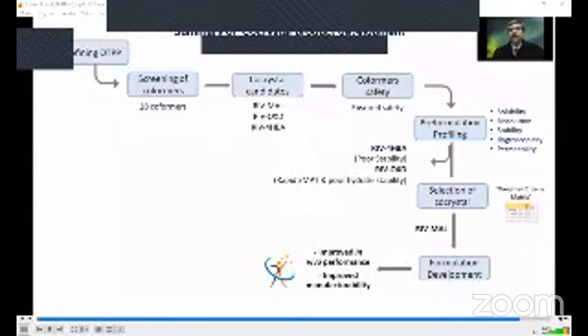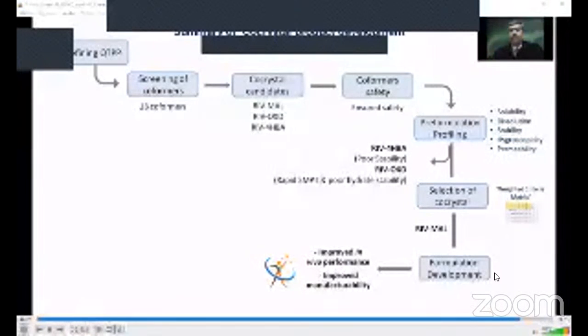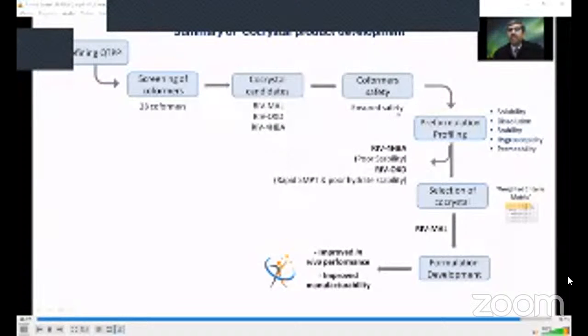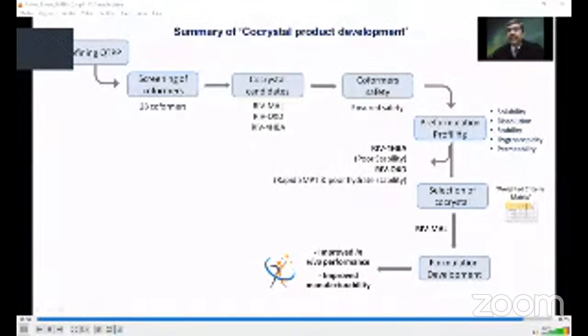Looking at developing a drug product from that co-crystal, the safety of the co-former must be ensured right in the beginning, because later on it is going to give problems with the regulatory approval process. This is followed by the pre-formulation profiling of the candidates or the co-crystal candidates that were shortlisted. Rivaroxaban 4-HBA co-crystal was rejected or not taken forward because of poor stability.